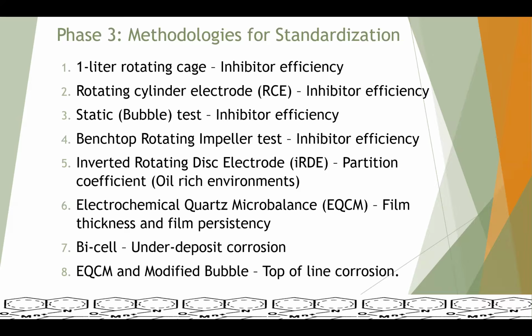Those 4 methodologies are, first, the inverted rotating disc electrode. This was identified to evaluate the partition coefficient of corrosion inhibitors, especially for oil-rich environments. Basically, this test will evaluate whether the inhibitor that was injected in the oil phase can reach the water phase in which corrosion occurs.